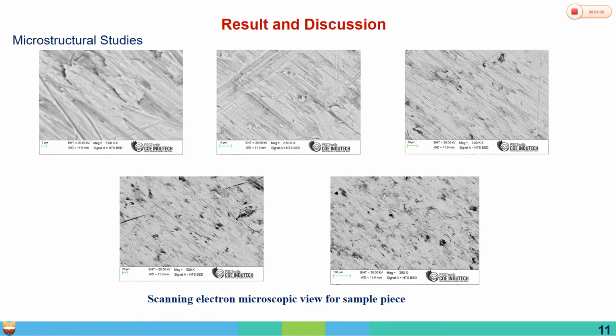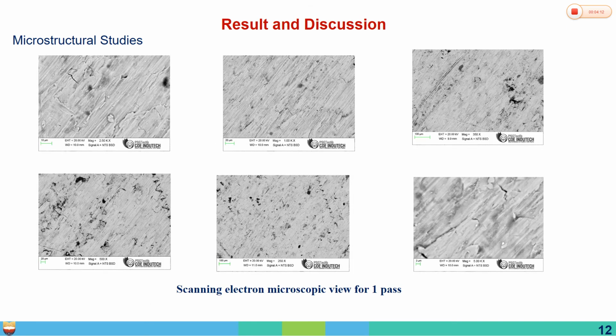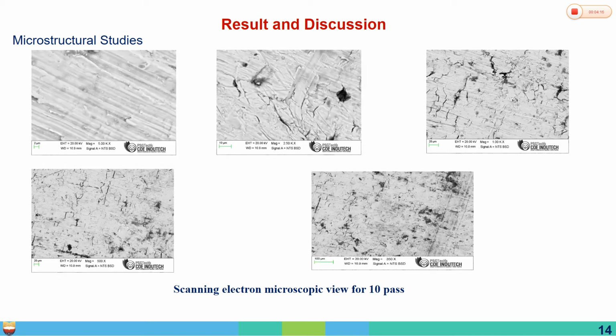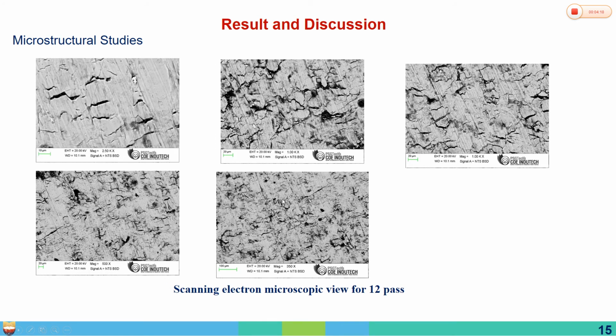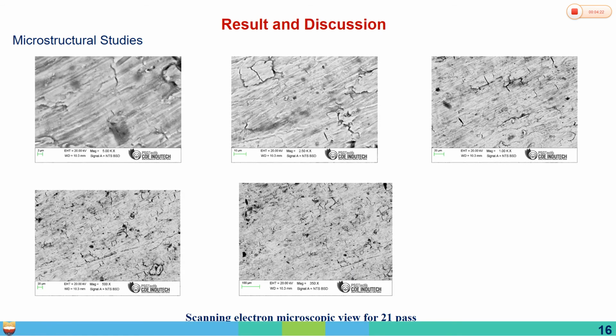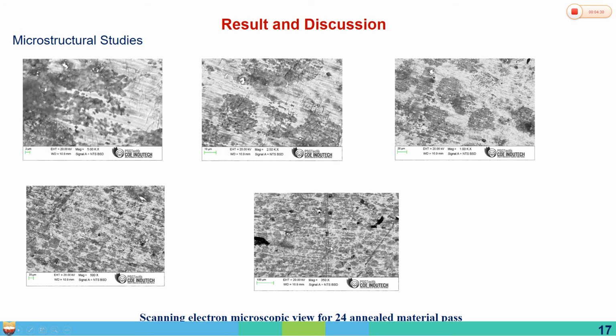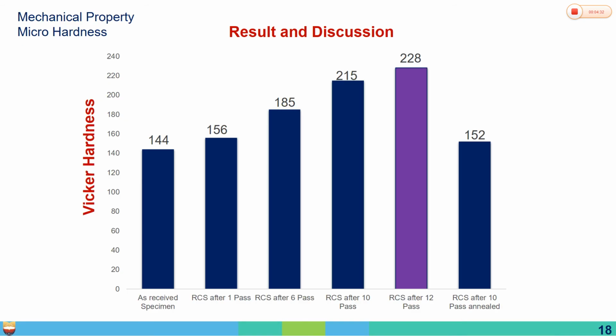Based on the SEM images, this is the raw specimen and this is the microstructure after 1 pass, and then the number of passes. After 12 passes, grain refinement and grain reduction take place. After 21 passes also you can see that grain refinement takes place, and after 24 passes in the annealed condition you can see it as well.